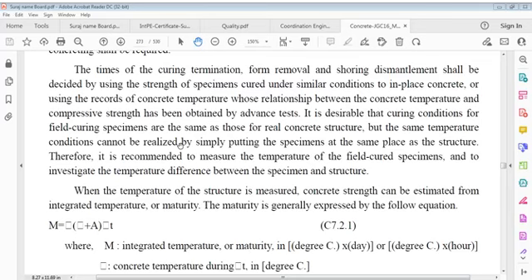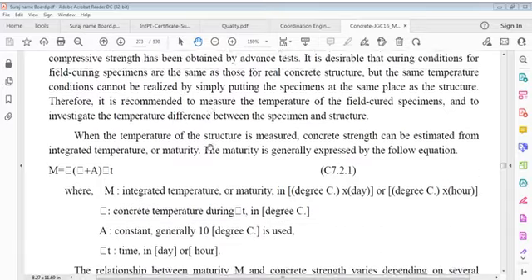It is desirable that curing conditions for field curing a specimen are same as those for real concrete structure, but same temperature conditions cannot be realized by simply putting specimen at same time at same place as structure. It is recommended to measure temperature of field cured specimen and to investigate temperature difference between specimen and structure.